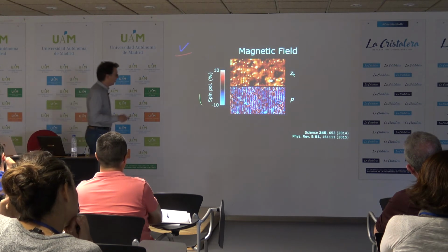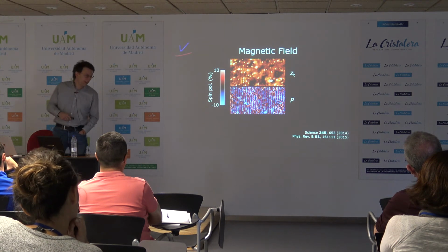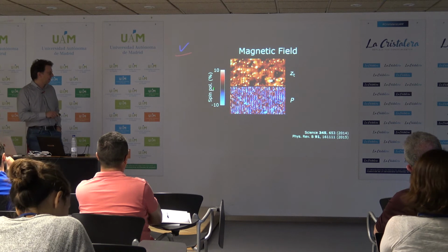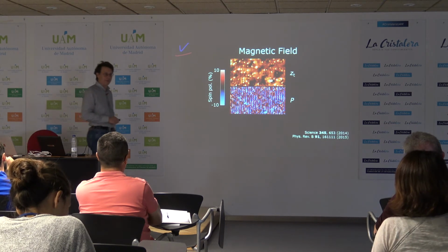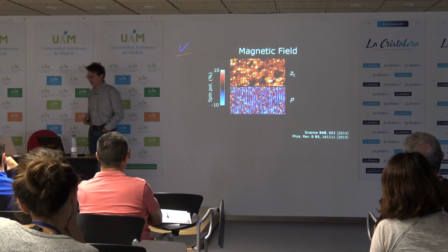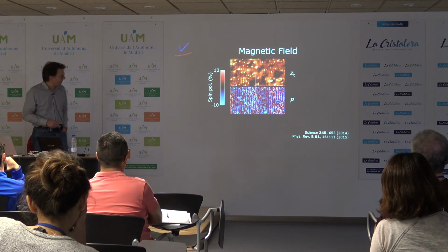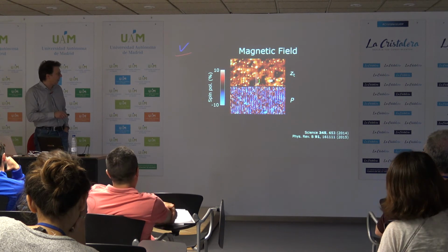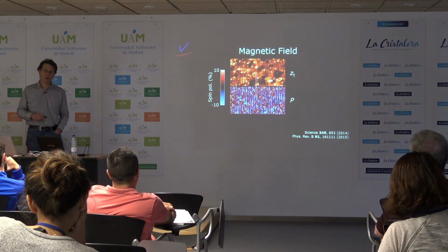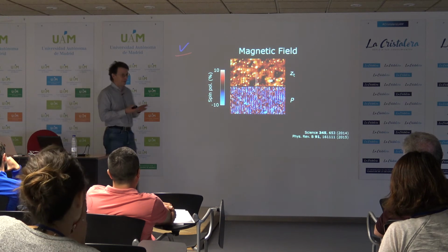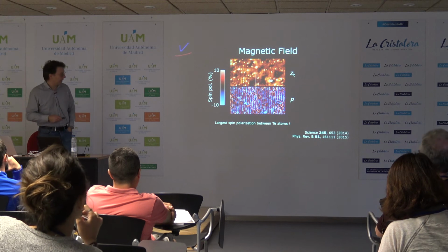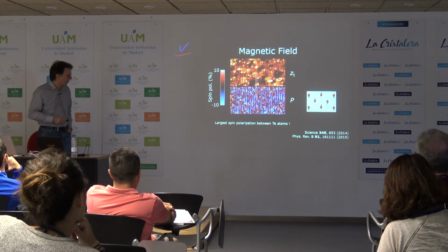If we do that, we can convert this to a proper spin polarization scale, and basically what it tells us is that the spin polarization across the sample here is up to 10% of the tunneling current in this specific case. In addition, you can also see that the maxima of the magnetic order occur between the tellurium rows, which is what you would expect because the magnetic order comes predominantly from the iron atoms and not from the tellurium atoms.